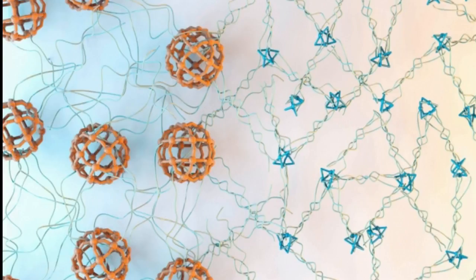When the researchers shine green light on the material, the ring is broken, the bond angle becomes smaller, and the smaller clusters reform. The process takes about 5 hours to complete, and the researchers found they could perform the reversal up to 7 times. With each reversal, a small percentage of the polymers fails to switch back, which eventually causes the material to fall apart.